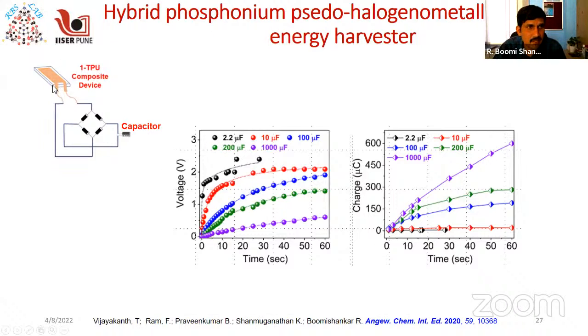And we see that by subjecting them to an external mechanical force, the capacitors can be charged within 60 seconds. The maximum storage points are reached within 60 seconds for all the capacitors, and the charge stored in the capacitors can be plotted from the voltage relationships. Q equals CV, where Q is the charge, C is the capacitance, and V is the voltage. From the output voltage, or the stored voltage, we can calculate the measured charges. So all the systems show very good charging of the capacitors,